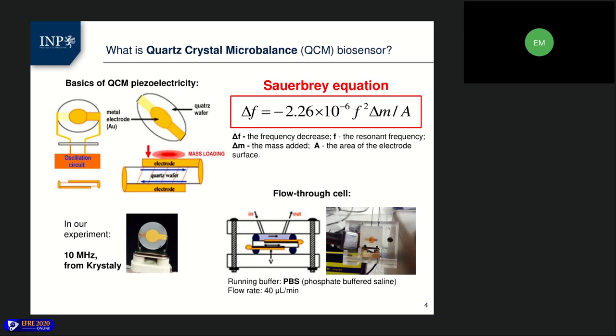The first sensing application was developed after Sauerbrey derived a formula for changes of the oscillation frequency depending on the mass loaded on the sensor surface. The bioreceptor, in our case antibody, immobilized on the surface of the quartz crystal, makes it highly sensitive to the target bioanalyte, in our case antigen. The bioanalyte binds to the bioreceptor and increases the mass loaded onto the surface, which directly corresponds to a decreased frequency of the resonator. Studies were carried out in liquid environment using a flow cell, and a phosphate buffered saline was used as a running buffer.